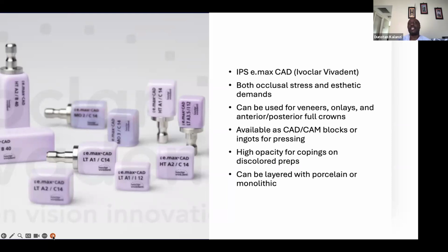What does that mean? You can cut back, so you can actually just have a core of lithium disilicate, and then you build up the facial aspect using your feldspathic porcelain. That way, you're able to maximize the strength of the lithium disilicate and the aesthetics of the feldspathic porcelains. So that is something that you can always ask your technician to do, but it can be done just with the lithium disilicate, or you can choose to layer it.